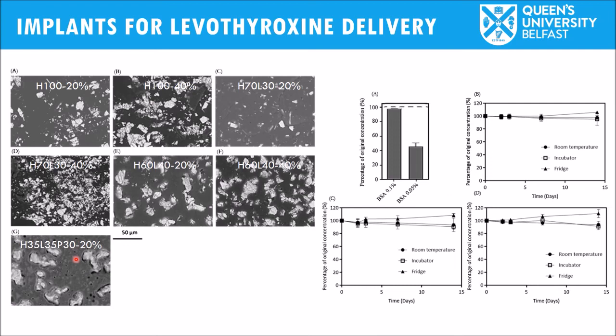Well, the implants were fine because there was no humidity, but it's quite challenging to test this compound in an aqueous environment for in vitro testing, when it's a highly unstable compound in aqueous environments. So we tried different types of solvents and co-solvents trying to stabilize it, and finally we discovered that the best molecule was BSA, or in other publications you can find that human serum albumin works too, so albumins. Why? Because this drug has a high binding to proteins, so it's stabilized.